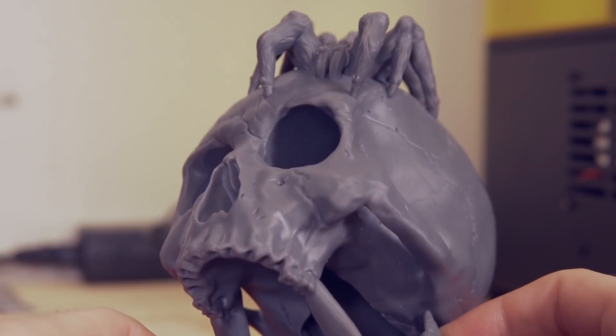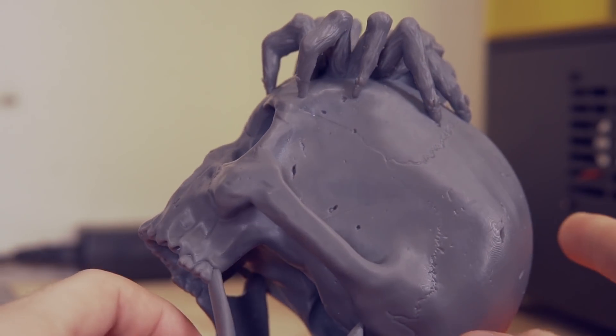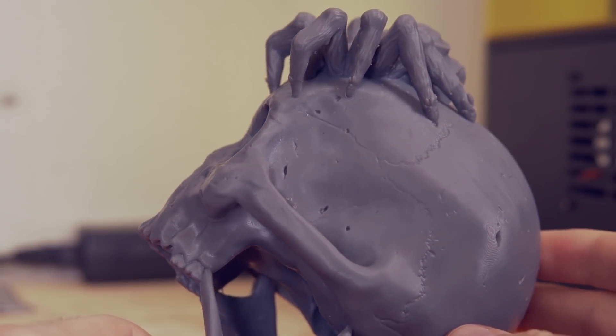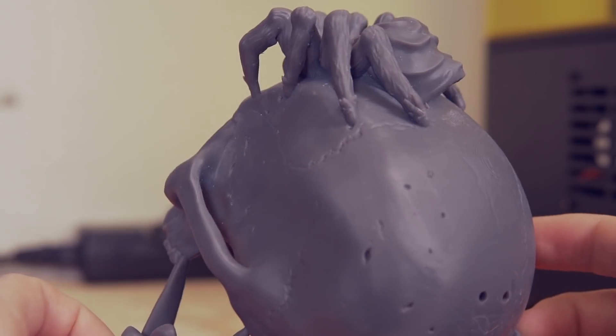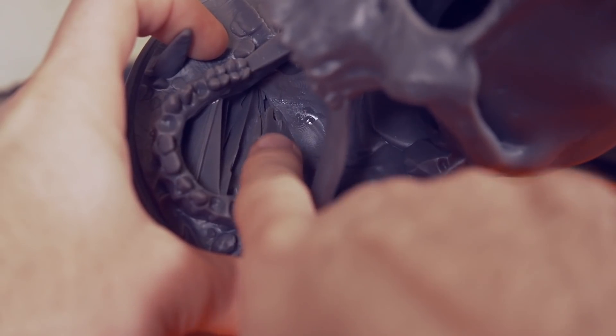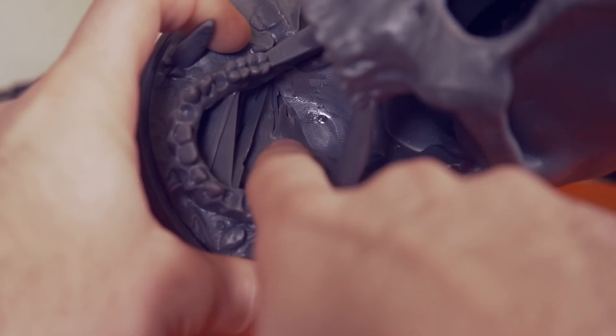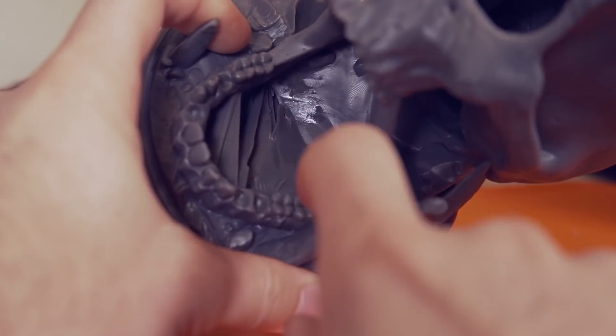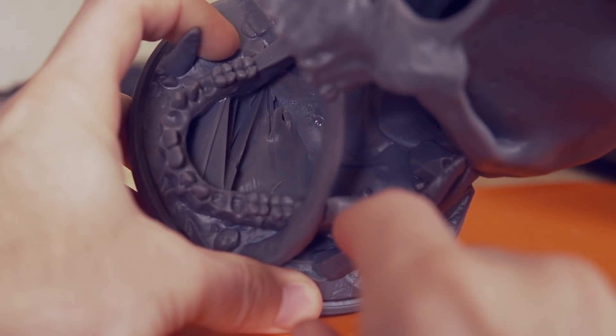And looking at the model, it is nearly perfect, but I did notice that on the inside of the mouth, there's actually a crack where there shouldn't be. This is very likely due to me not having drain holes in the base. I did include two in the back of the head, but I didn't actually realize there was a separate hollow cavity down below. What I think happened was from the printing process with the resin hardening, it looks to me like it's some sort of a stress fracture. Typically, on larger resin 3D printers, they recommend having a certain amount of drain holes for large prints, especially if they're hollow, because it helps if there is any sort of flexing or the part shrinking or expanding. It helps to prevent any sort of those fractures. But it is hidden in the mouth, and it is actually next to a split that's supposed to be there because of the model, so you can hardly tell. And again, the rest of the model just turned out absolutely perfect.